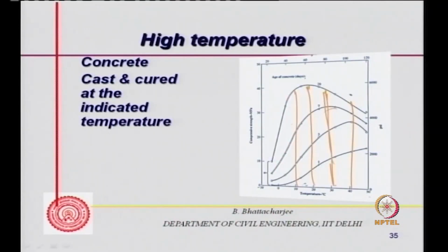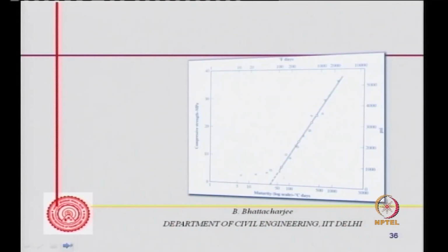So with higher temperature, early strength gain is high. But the later 28 days strength actually reduces. So maximum 28 days strength you are getting at 20 degrees centigrade, when you are casting and curing at the same temperature. All right.